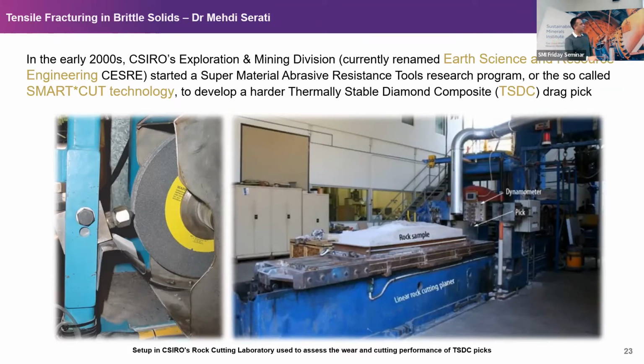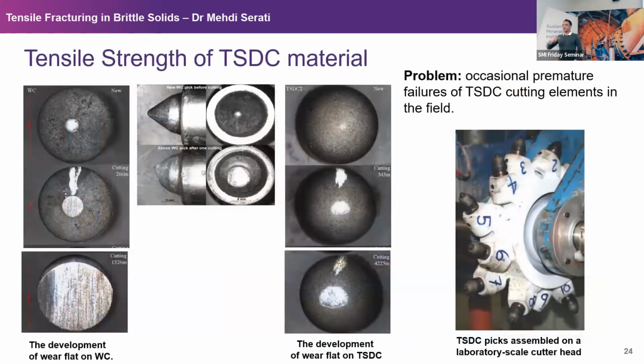And this is a type of setup that was available at the time. You see, for instance, we have a single cutter, which makes a single groove. So we have a very strong rock, say 200 MPa, and you have the cutter here, and then you move it and scratch the surface, and observe the force and the development of wear on the cutting element. Very interesting result. It was not generated by me. I had access to this result.